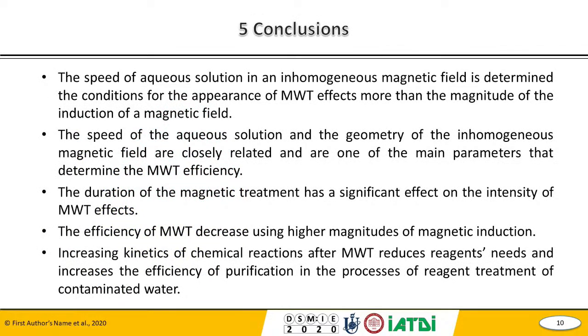I want to note that the speed of aqueous solution in an inhomogeneous magnetic field determines the conditions for the appearance of magnetic water treatment effects more than the magnitude of the induction of the magnetic field. The speed of aqueous solution and the geometry of the magnetic field are closely related to each other and are one of the main parameters that determine the efficiency of the process. The duration of the magnetic treatment has a significant effect on the intensity of the effects, and efficiency decreases using higher magnitudes of magnetic induction.